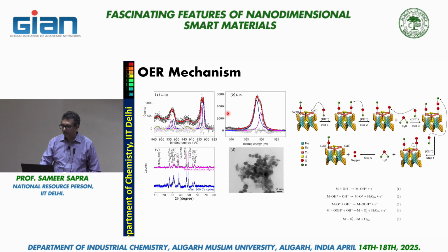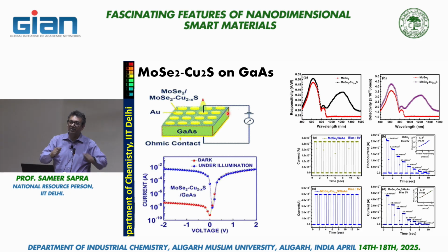We can also do the hydrogen evolution. There's a mechanism also, because these are type 2 kind of heterostructures. We also made some very interesting photodiodes. And if you look at these photodiodes, then you see, this is current and that's voltage, except that it's plotted on a log scale, to clearly amplify these differences. If you look on the right side, you see both dark and bright under illumination, they are exactly the same. But in the reverse bias conditions, this is your dark and that's your bright. The on-off ratios are 10 to the power 5, 1 lakh times.